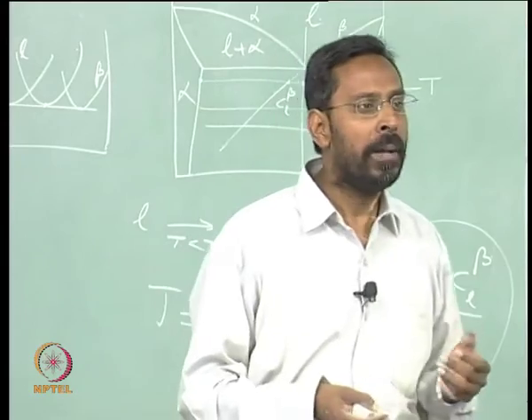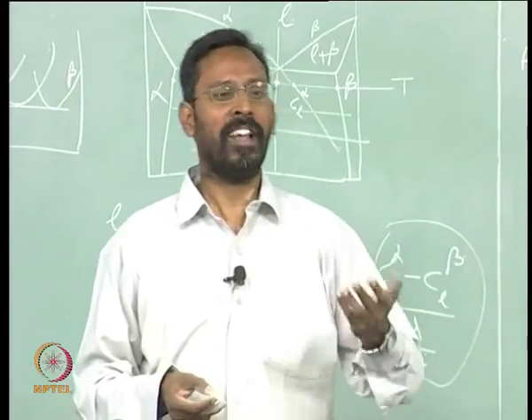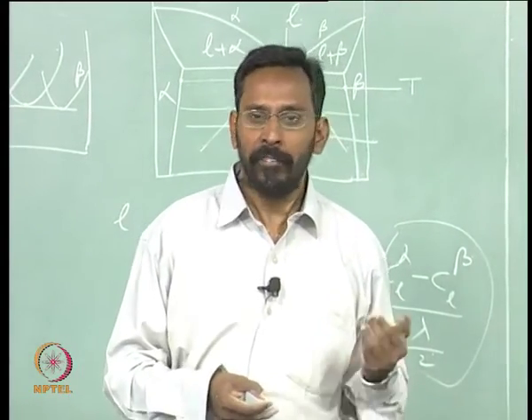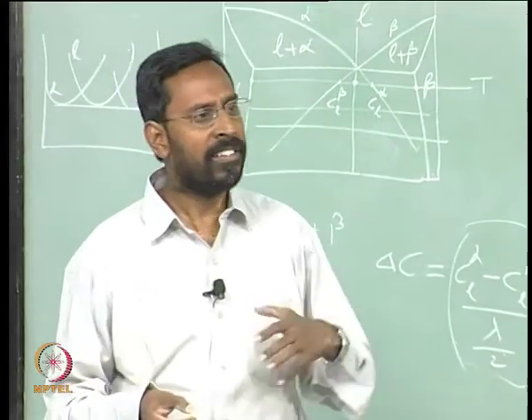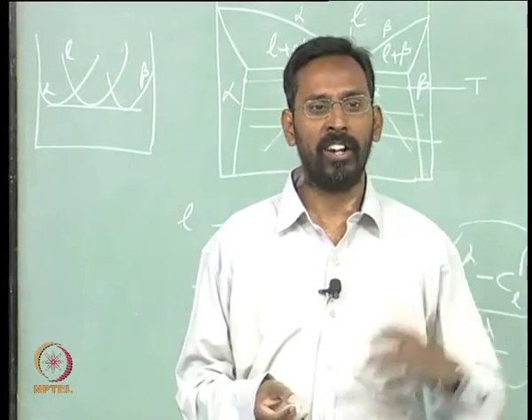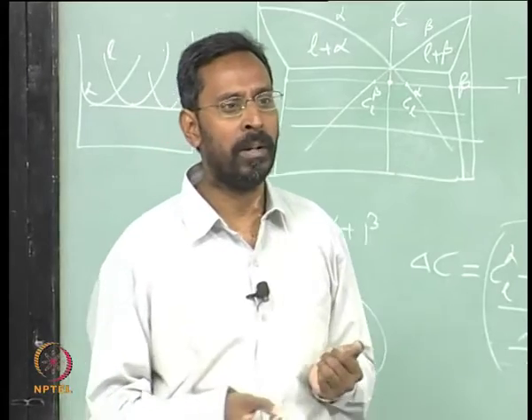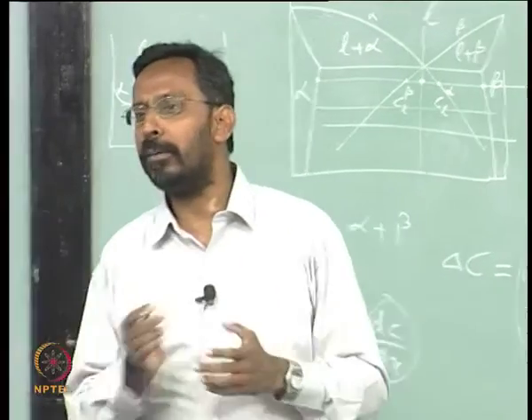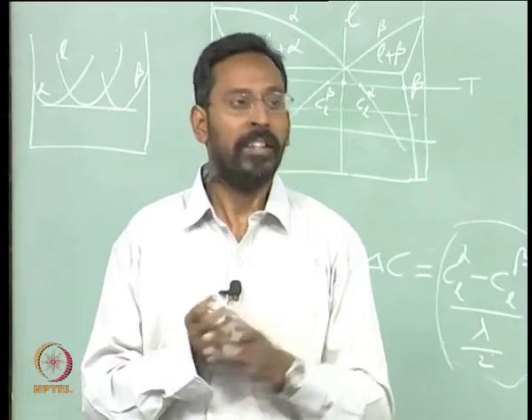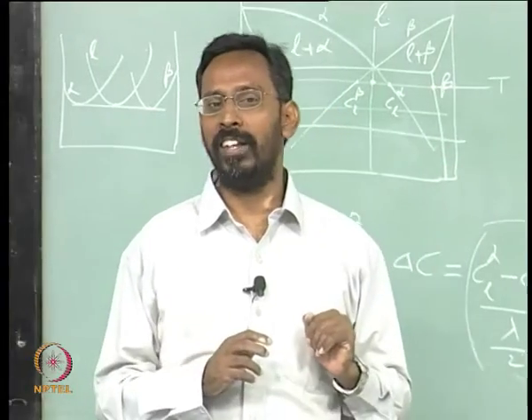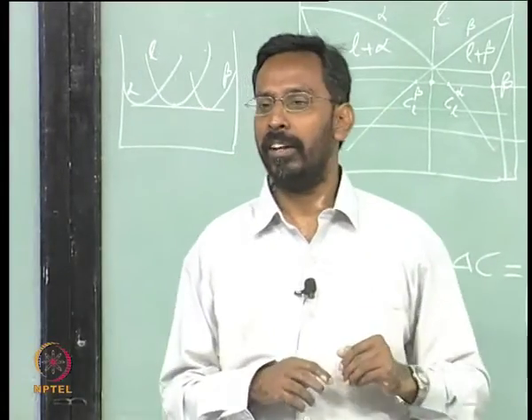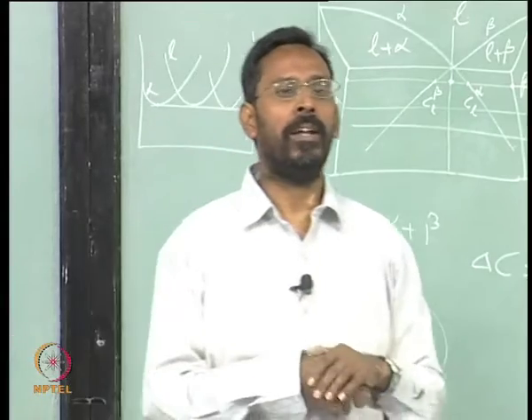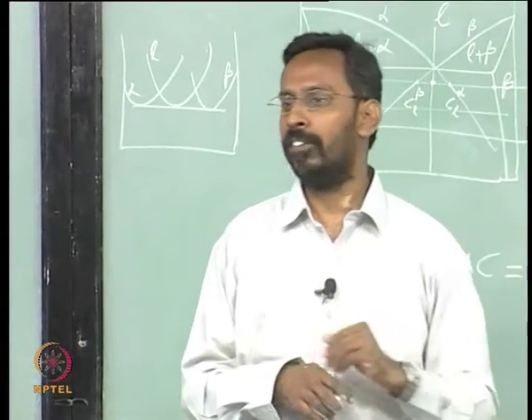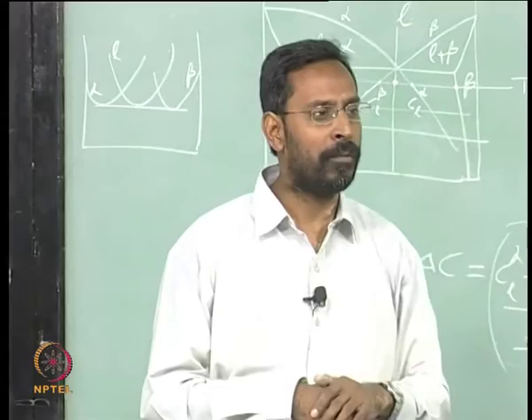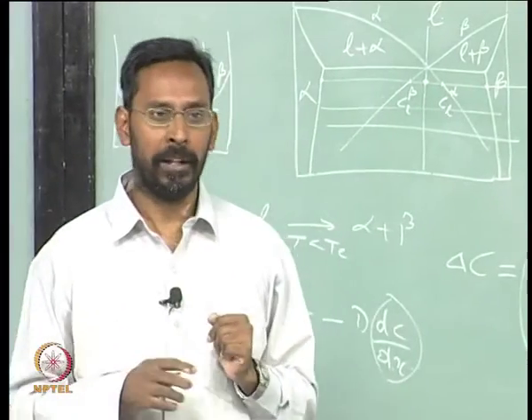Why? Because TiB2 has a hexagonal structure, and whenever you have a hexagonal structure, there is some similarity with aluminum. What is the structure of aluminum? FCC. What is the similarity between these two? Some plane of FCC has similar packing to that of another plane in HCP. The basal plane of HCP and the 111 plane of FCC have exactly similar packing.